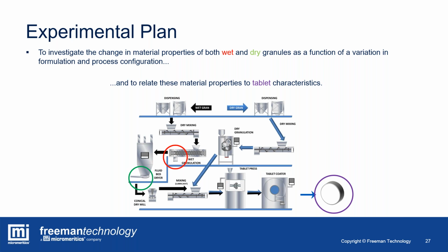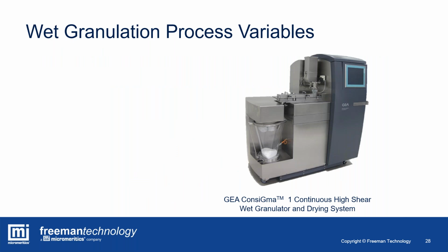And so here you can see the Consigma 1. It's a high shear wet granulator and drying system from GEA, and it's a highly versatile bit of equipment because it allows you to scope process settings very quickly. And what you have in principle is a loss in weight feeder and a hopper here that contains your pre-blend. That is metered into the screw. Sorry, the image is quite small here. This rectangular object on the top here is the twin screw granulator element itself.